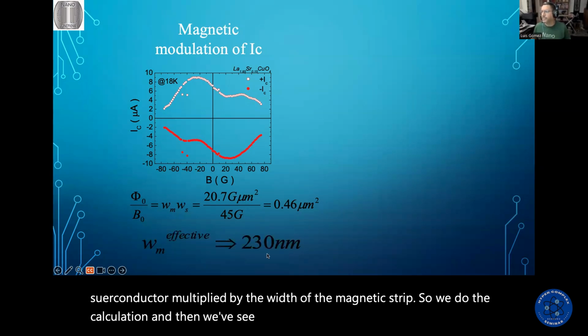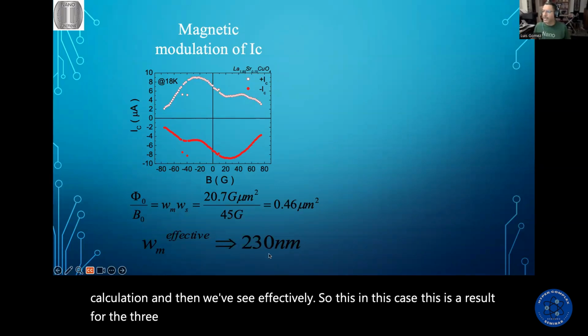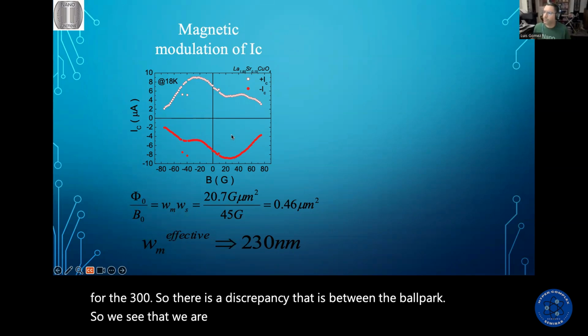So in this case, this is the result for the 300 nanometer sample. There is a discrepancy, but it's in the ballpark. So we see that we are satisfying this equation for the strip of 300 nanometers.